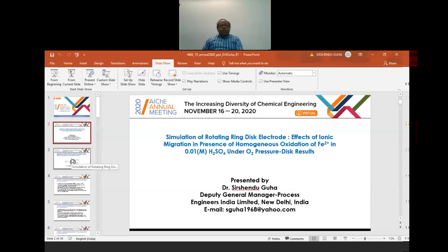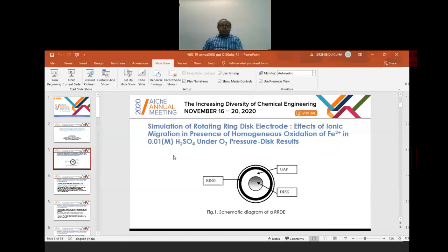Now, what is an RRDE, or rotating ring disk electrode? The picture of a rotating ring disk electrode is given here. It consists of a disk, a gap, and a ring. The disk and the ring are all concentric. The gap is generally made of PTFE. The disk and the ring are made of platinum. Now, my research work is on the usage of this rotating ring disk electrode for finding out the effects of ionic migration in presence of kinetic complications of oxidation of ferrous in sulfuric acid under oxygen pressure.